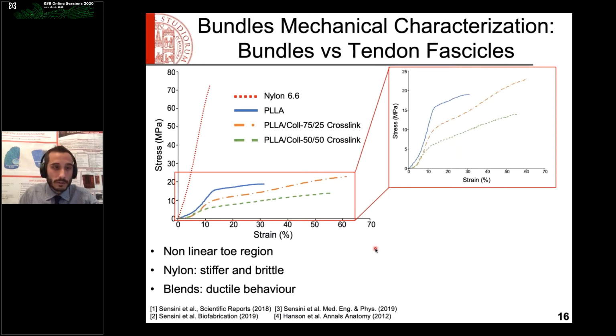Here are the results in terms of stress and strain for the different bundles. In red, you can see the nylon 6/6, in blue the pure PLA, the 75-25 cross-linked blend in orange, and the 50-50 cross-linked blend in green. In this box, you can also see a zoom in of the regenerative bundles.